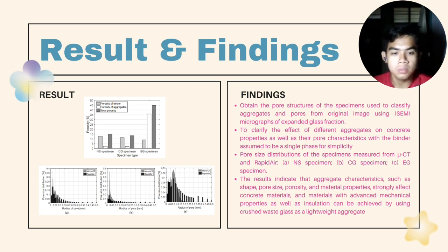For the graph, the pore size distribution of the specimens was measured from μ-CT and RapidAir, where graph A is the NS specimen, graph B is the CG specimen, and graph C is the EG specimen. The results indicate that aggregate characteristics such as shape, pore size, porosity, and material properties strongly affect concrete materials. And materials with advanced mechanical properties as well as insulation can be achieved by using crushed waste glass as lightweight aggregate in construction concrete.